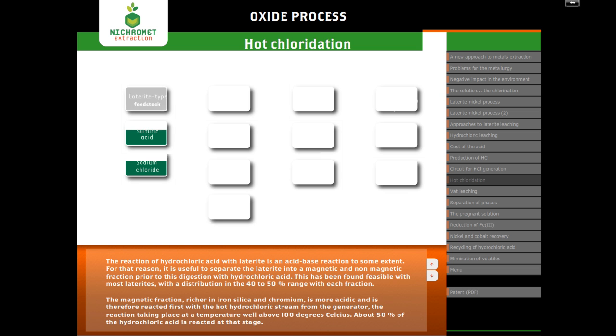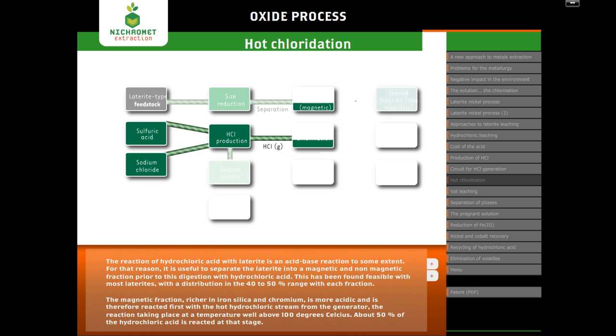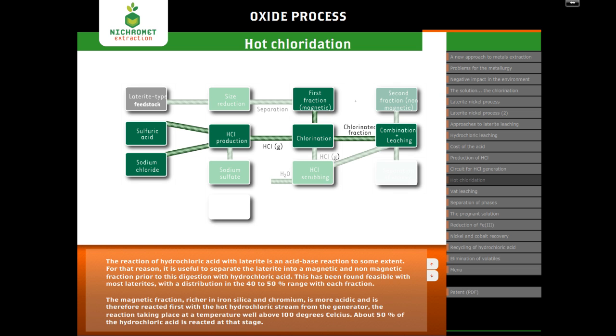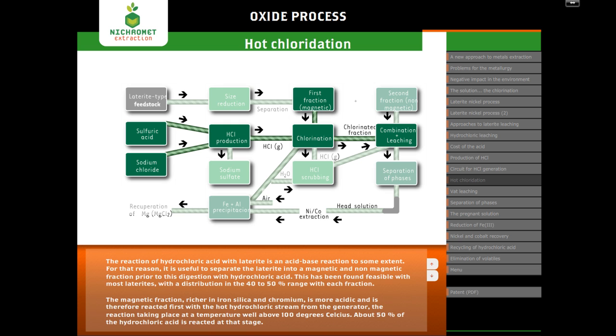Reaction of hydrochloric acid with laterite is an acid-base reaction to some extent. For that reason, it is useful to separate the laterite into a magnetic and non-magnetic fraction prior to this digestion with hydrochloric acid. This has been found feasible with most laterites, with a distribution in the 40 to 50% range with each fraction. The magnetic fraction, richer in iron, silica, and chromium, is more acidic and is therefore reacted first with the hot hydrochloric stream from the generator, the reaction taking place at a temperature well above 100 degrees Celsius. About 50% of the hydrochloric acid is reacted at that stage.